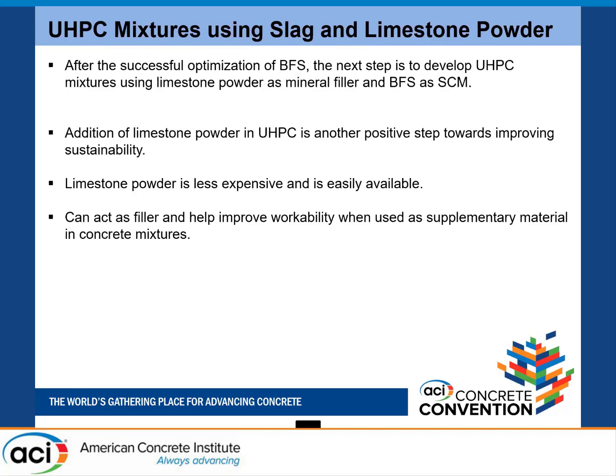So we have to see how slag will react with limestone, because we have to get ready for practical conditions that can occur anytime in the future. Right now we are only looking at the interaction of slag and cement, but now we have to see the interaction of slag with limestone cement. That's an important point. That's why we included it in our research.